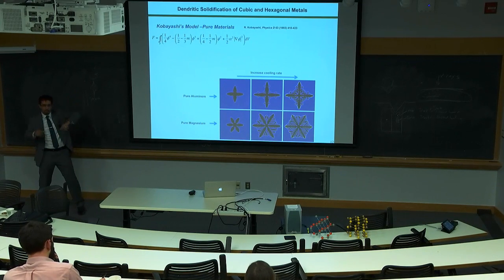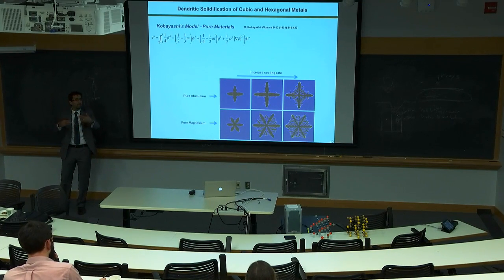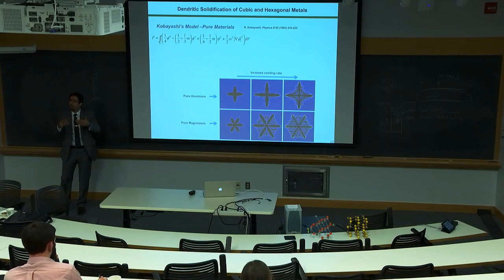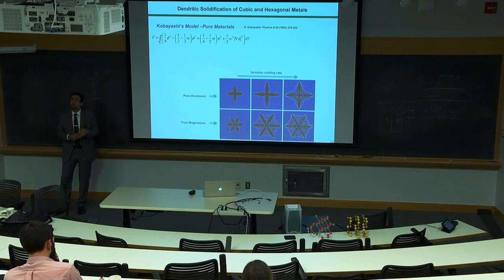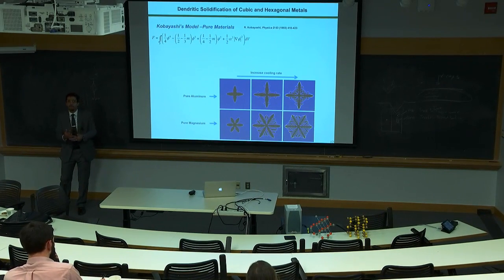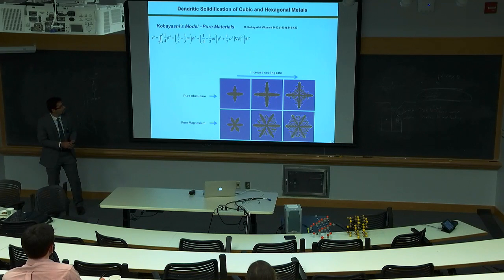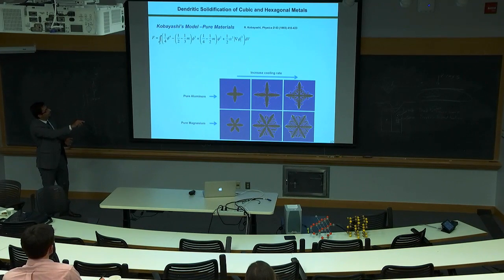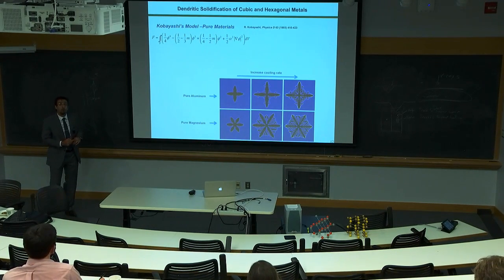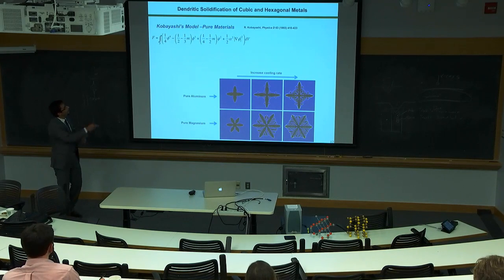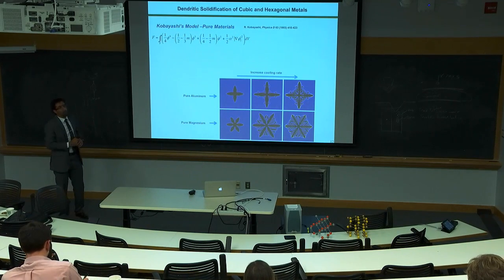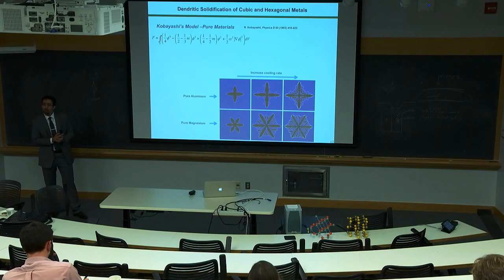Here also, you have a domain. You have different phases, different grain boundaries, different interfaces. All of those have some kind of energy. Like every phase has formation energy. Grain boundaries have grain boundary energies. Interfaces have interface energies. So if you can put together a functional, which we call total free energy functional, then you are going to make a phase field model.